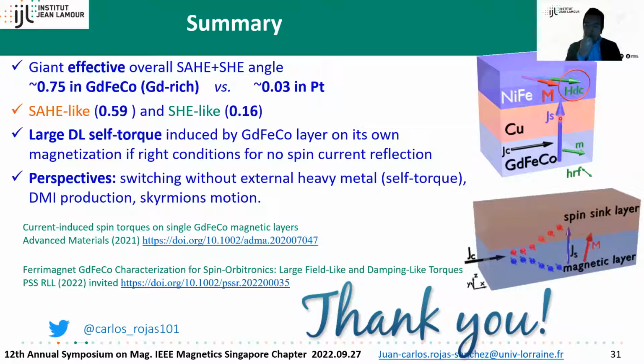No, in this case, thank you. That's a good question. Actually, gadolinium, or ferrimagnets in general, have a large spin-orbit coupling, so the thicker the ferrimagnet, the higher the perpendicular anisotropy, so it's more robust and more stable to have this magnetization out of the plane.